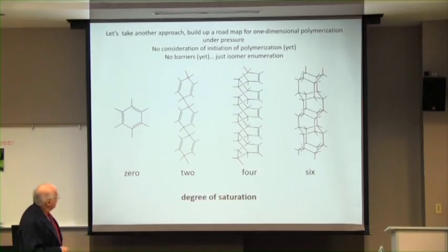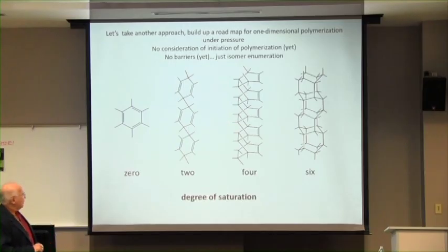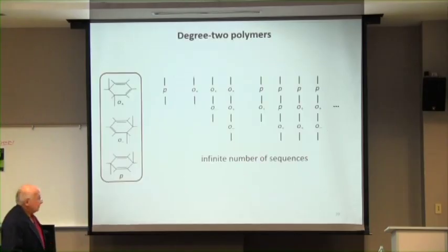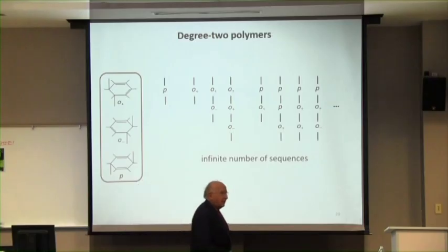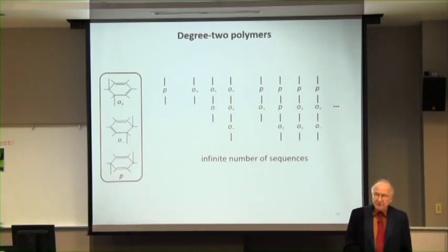So there is the question of how the polymerization takes place. But we thought what we could do is to provide a roadmap for going from this to that by constructing all the possible isomers, possibilities for polymers along the way, which had, if you call this 0 degree of saturation, and this 6, the ones with 2 and 4. And why didn't we do 3 and 5? Because those are radicals. And we were looking here for the stable waypoints in this. So how to enumerate these? So you start to do this, and it's lots of fun. And it brings up lots of things from organic chemistry.